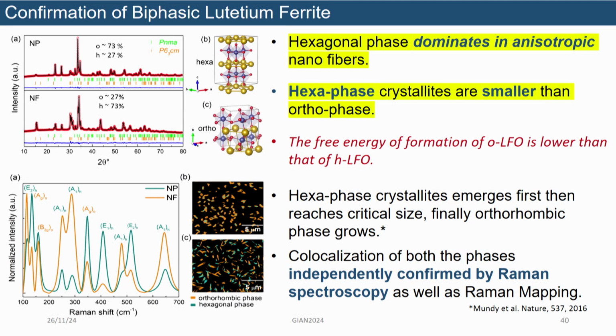So we got more interested, okay, we should investigate this instead, and we realized when we did the Rietveld analysis of the X-ray diffraction data, the structural data, what we found was that in the nanoparticle we got 73% orthorhombic and 27% hexagonal, and in the nanofiber it is exactly opposite, while they were synthesized at the same temperature.